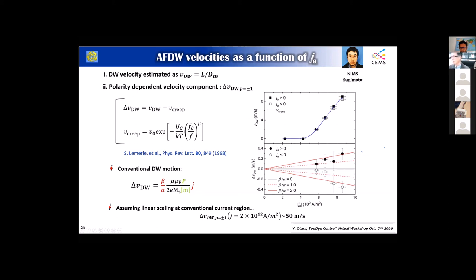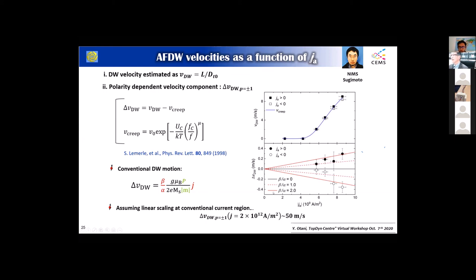The bad news is we didn't see much current polarity dependence — the velocity always goes up. Also, since this sample has a wedge shape, that also drives the domain walls. We fit this part with a creep equation, and the difference between the total velocity and the polarization dependence can be determined as the difference between the two. We analyzed this difference using a conventional spin transfer torque model, setting beta over alpha — a coefficient of the damping constant and momentum dissipation — in three cases: 0, 1, and 2. The result sits in between, but it's not that small.